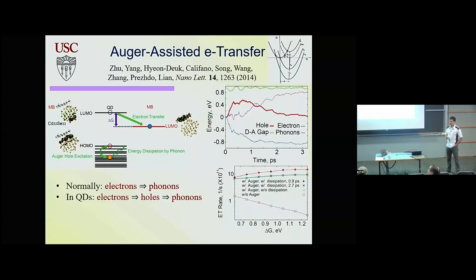It's competing with the electron or hole transfer. And in molecules, we don't think about it this way because we never have charges on the surface or excite another exciton in a molecule. Very different regime. So, if you think of excited states not as electrons and holes, but as excitons, you basically have many excited states. And then your Marcus model can still work, but you have to include excitation of the hole, of the other charge, in addition to that.